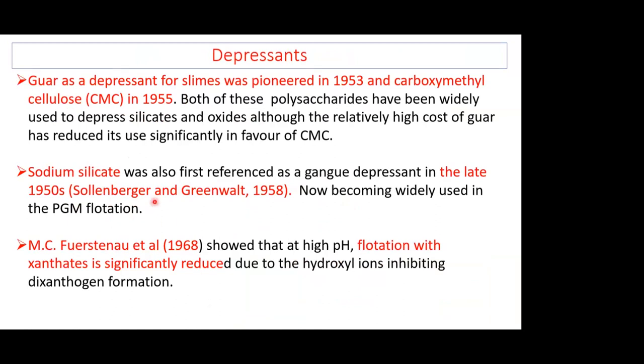Depressants are referred to, guar and CMC. Sodium silicate, gaining a lot of interest today, is a depressant developed in the late 1950s by Sollenberger and Greenwalt, and now very widely used in the PGM industry. And M.C. Fuerstenau in the 1960s showing that at high pH, so the controlling of the flotation of different sulfides, especially of pyrite, which is a big challenge, to control flotation of pyrite using pH.